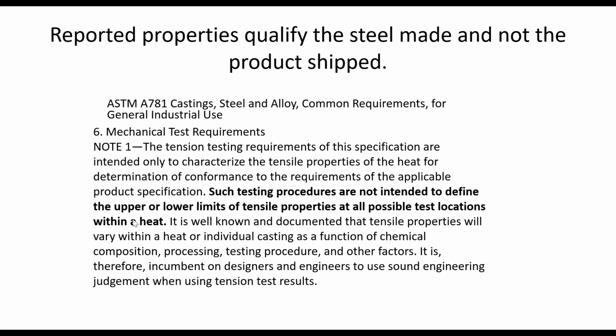So you get a casting and you cut it up and you take tensile specimens out of it. Some of them will be higher than the properties we report. Some of them are likely to be lower, especially if you take them from the center line where there's some segregation and porosity.